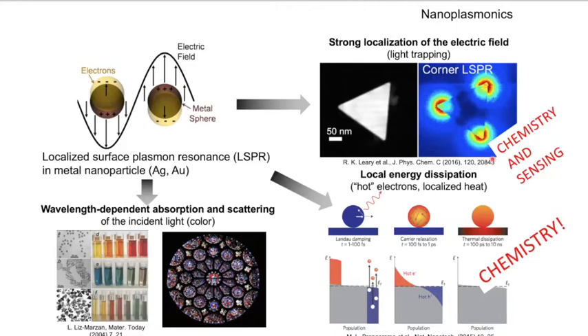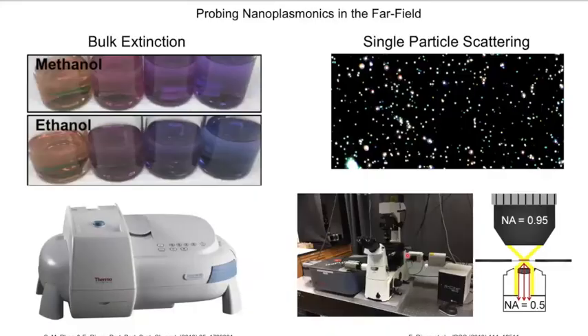Very recently, there's been a lot of push for doing chemistry actually with the decay product of this resonance. When the resonance decays, it creates non-thermally equilibrated electrons and holes. Some people call them hot electrons, okay? And then it turns into basically heat. This is all a way to harvest a photon, turn it into another mechanism that can give energy to a chemical reaction and give rise to enhanced reaction rates, for instance. There's a lot of ways to look at plasmonic effects.